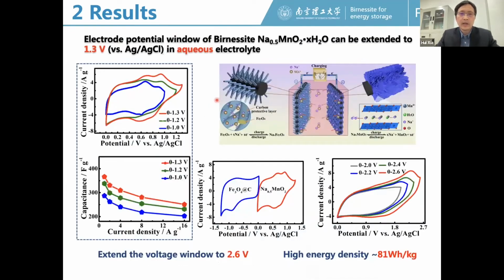And by using this high sodium content Birnessite, we can extend its potential window in the aqueous electrolyte. And by using this sodium Birnessite, we successfully constructed a 2.6 volt asymmetric supercapacitor in aqueous electrolyte. So by extending this voltage window, we successfully increased the energy density to about 81 watt-hour per kilogram for this supercapacitor. But nevertheless, this method is still not efficient enough to obtain a high sodium content.